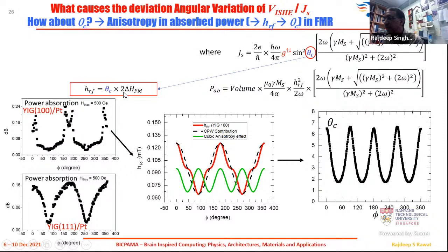Now, the precession cone angle can be deduced by this expression, where it is going to depend on the h_rf field that is applied and the linewidth. We already have shown the linewidth value, so we needed to find out the h_rf. One way to find out h_rf is to use the simple equation, B equals mu naught I divided by 2 pi r. So how much current you are sending in the waveguide, you can just use to calculate, but that will be a very approximate ideal value. We found it experimentally by finding out the power that is being absorbed by our films.